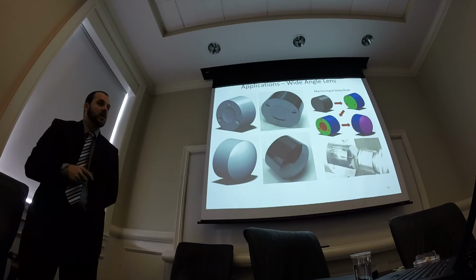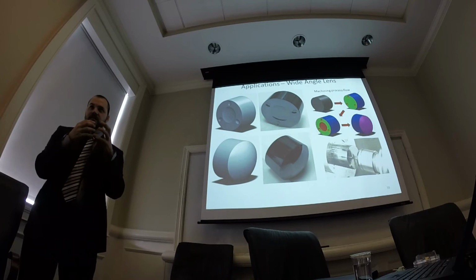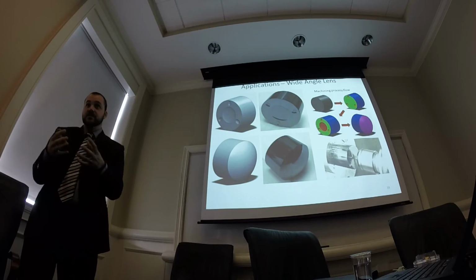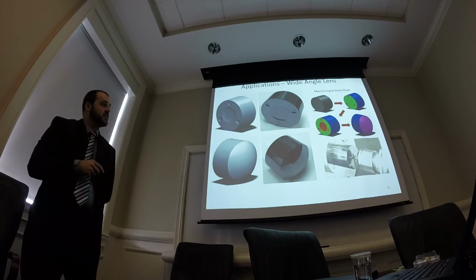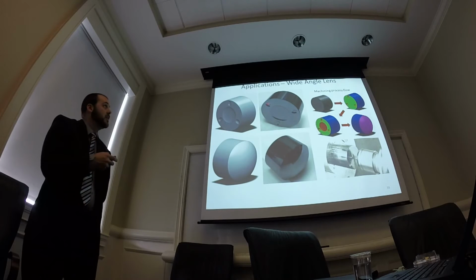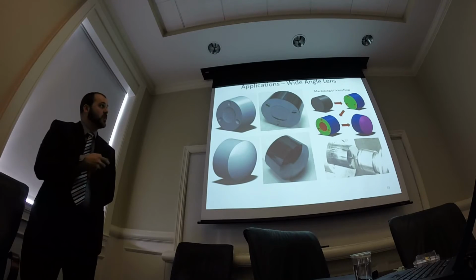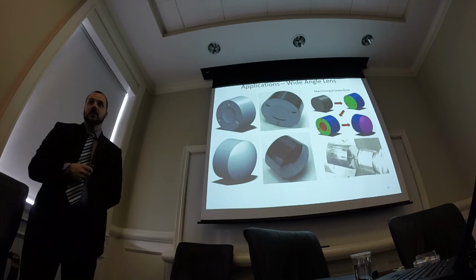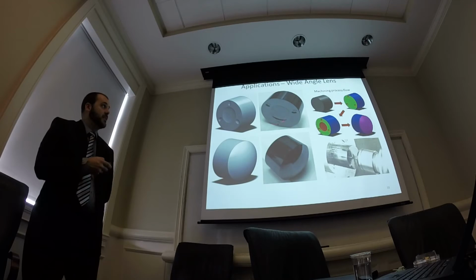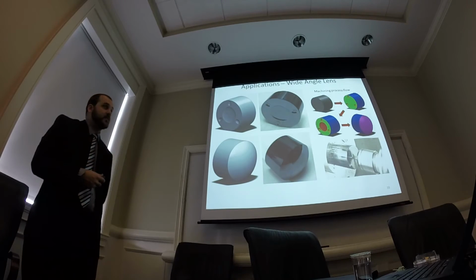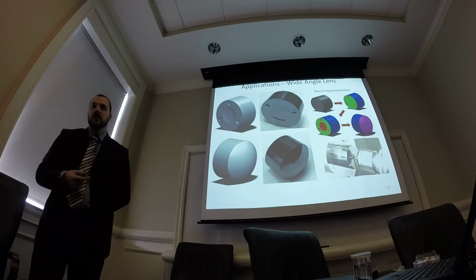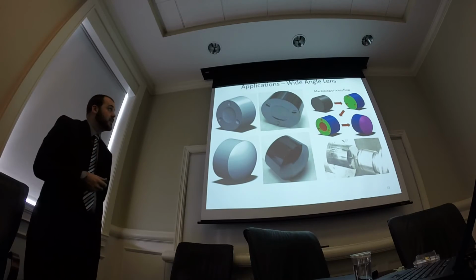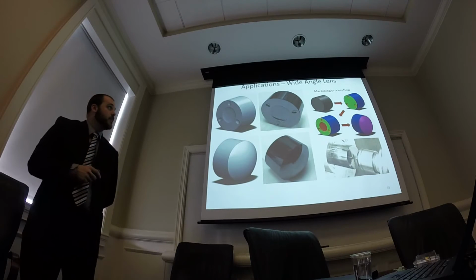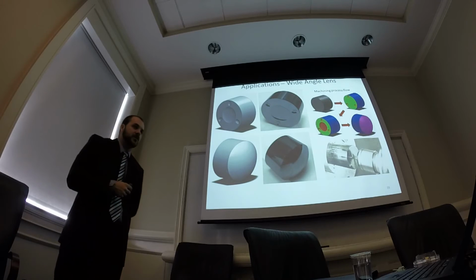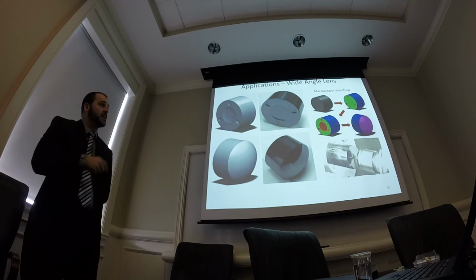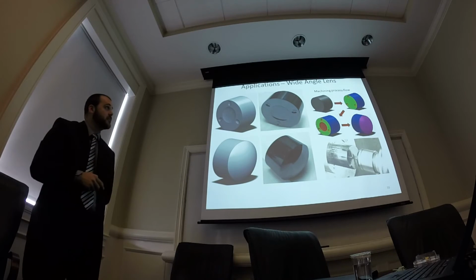So we added these to show, if we had two optical elements with some very specific distance between the two optics, which is typical, can we machine these optical tolerance level features - so this is 3 grooves - can we put 3 balls on another optic, seat them together, and have them in the 100 nanometer range tolerances, where what I typically see between two lenses is a couple microns, not a couple hundred nanometers. So with this, we could conceivably achieve optical level tolerances in assembly without needing to measure while we did the assembly. That's why we stuck those features on there.